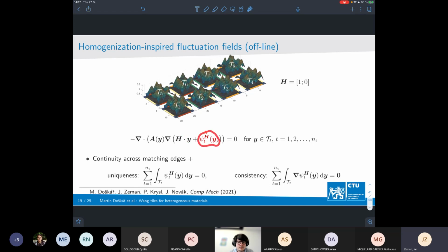On top of that, we add a certain correction or fluctuation, if you wish. And this is again written down for every tile in our set, as visualized here for 8 tiles only. We also require that this enriching function will be continuous across matching edges. So this is again this multi-periodicity constraint occurring directly in our formulation.